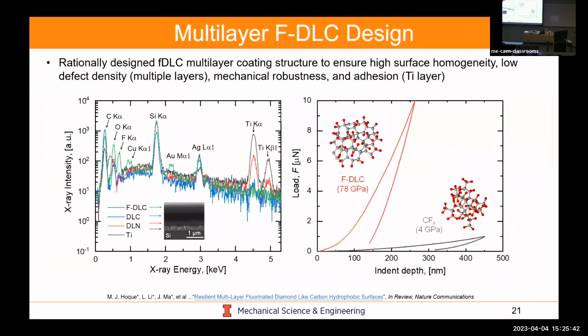So you can look at X-ray intensity as a function of X-ray energy. This is basically an XPS scan. And this FDLC coating, which I'm showing you here, is about 2.5 microns thick, but it's got multiple layers. It's got a titanium layer for adhesion. It's got a nitrogen-rich layer for certain thermal properties, a silicon-rich layer, and then a fluorine layer that's co-deposited with DLC on top, which is about 600 nanometers thick. And so the top layer gives you the function.